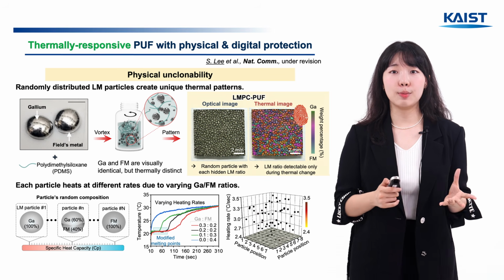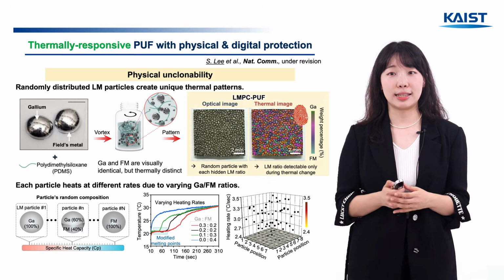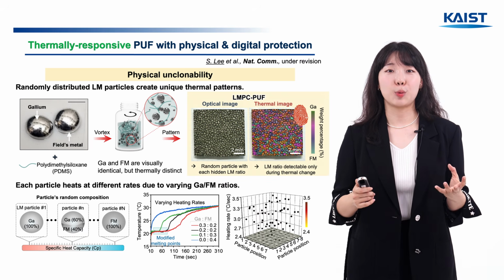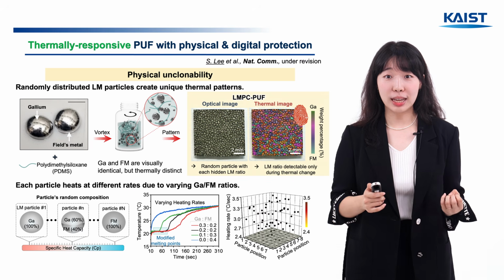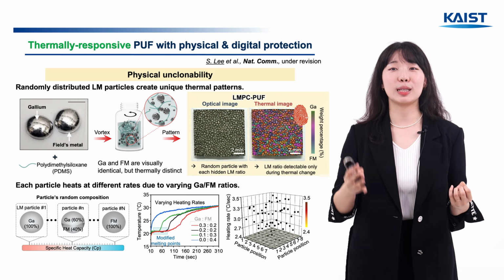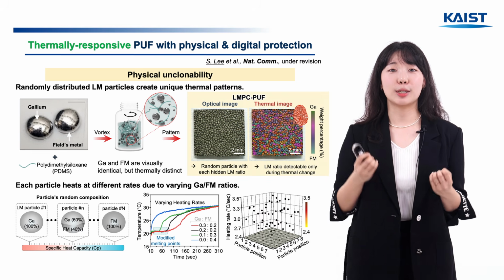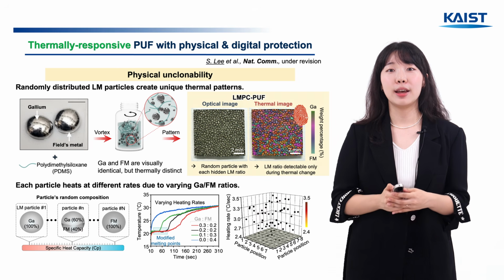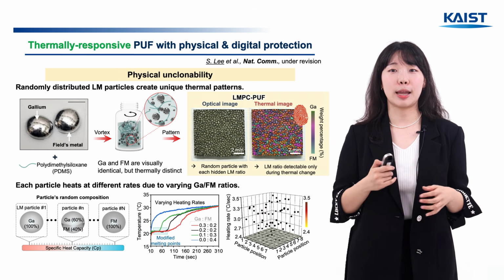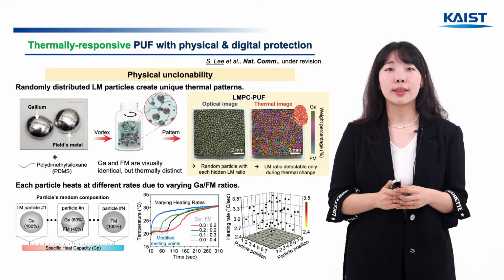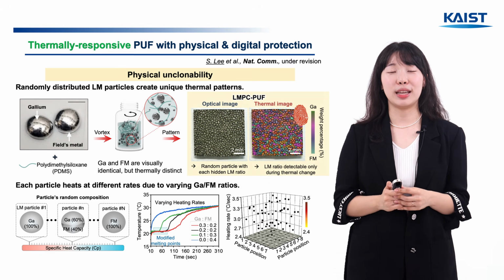But because gallium and Field's metal have different specific heats, particles with more gallium heat up slowly, while particles with more Field's metal heat up quickly. So when you apply heat to the PUF, each particle rises in temperature at a different rate, giving each PUF its own unique thermal pattern.